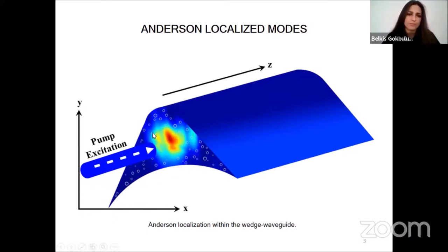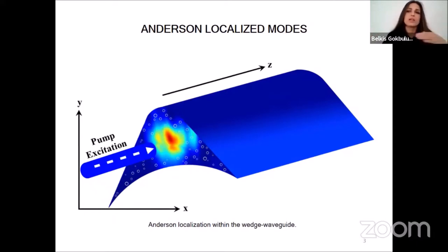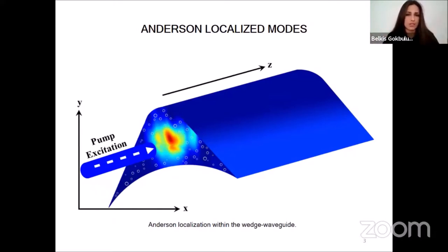In the first part of our study, transverse Anderson localized modes are firstly generated inside a simple wedge-type optical waveguide through excitation of the dye molecules embedded into the structure. A probing beam entering the disordered medium of the waveguide structure consisting of air inclusions within the polymeric medium is demonstrated. The different color regions describe the intensity distribution of the interference pattern due to transverse Anderson localization. Transverse Anderson localized modes are accomplished through several single optical modes appearing at different emission wavelengths within the spectral bandwidth of Rhodamine 6G dye molecules, and the photonic design of the structure allows guidance of a single dominant Anderson mode and suppression of the others.